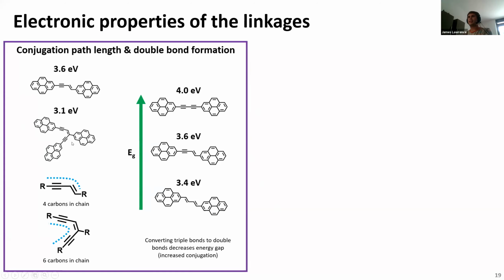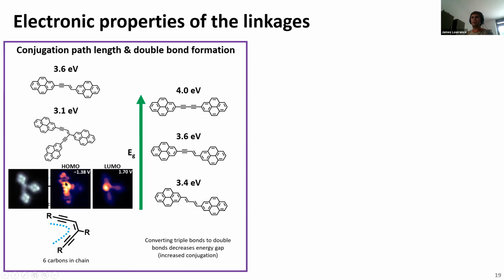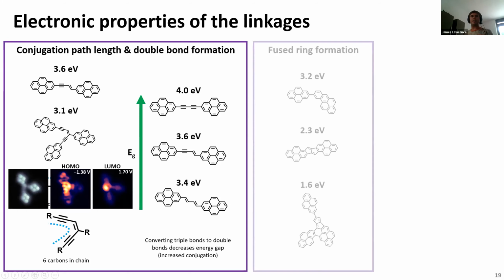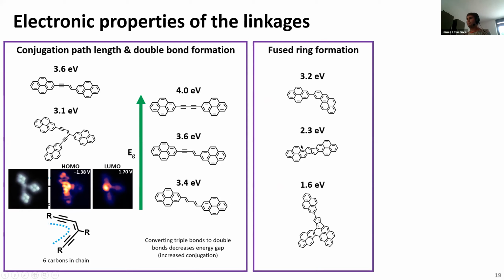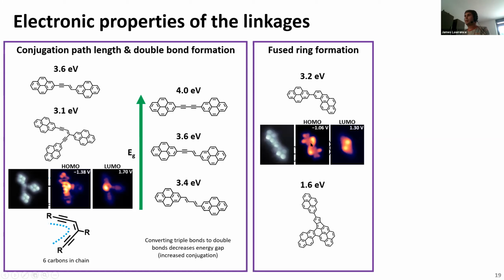And you can also try to rationalize things in terms of conjugation path length, the longer path reducing the gap. This is probably not a great example because we've still got these triple bonds, but when you form this molecule, in comparison to this one, you get quite a significant concentration of these frontier states around this junction in the middle here. So this is the HOMO and the LUMO. As I said before, we can also consider the formation of fused rings. Naturally, as we increase the number of fused rings attached to the pyrenes, we really reduce the energy gap. And again, this is very apparent in the imaging, as we see, for example, in this dimer with two 5-membered rings, where we see a real concentration in this connection.